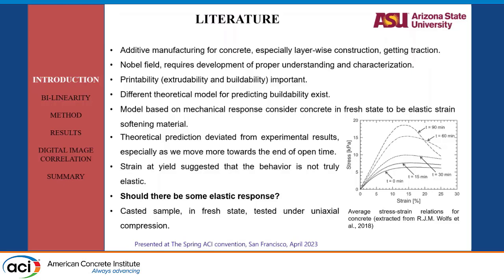The question came up. When you observe a mechanical test stress-strain graph for fresh concrete, we usually call this region elastic. When we say elastic, it should be able to go back to its initial state when we remove the load. But seeing the strain here, we are sure that a 15% strain can't be recovered by the concrete. So the question came up: is there an elastic response for the green concrete?